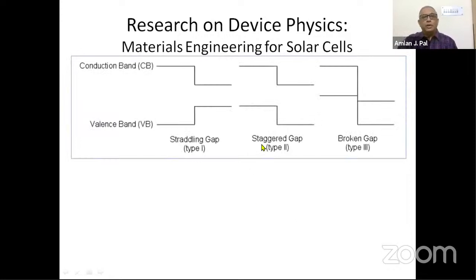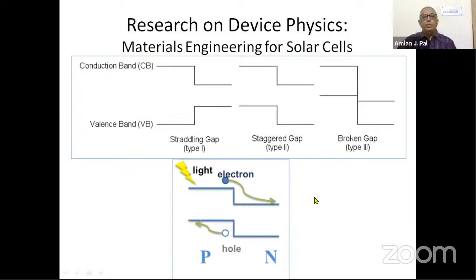So type 2 band alignment. There are different types of band alignments we call type 1, type 2, and type 3. In type 2 band alignment, the two materials form this kind of staggered gap. And we need this kind of staggered gap junction in most of the devices, especially in solar cells, because if we have a junction like type 2 band alignment, then upon excitation with light, they will